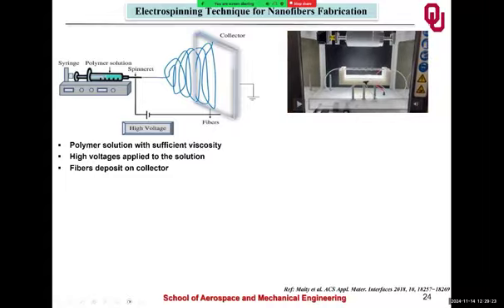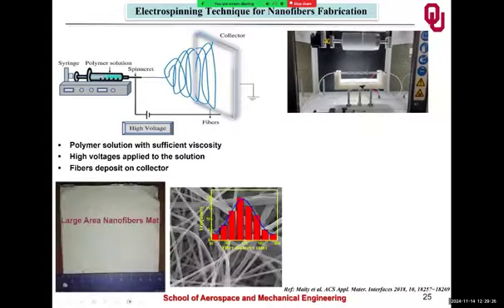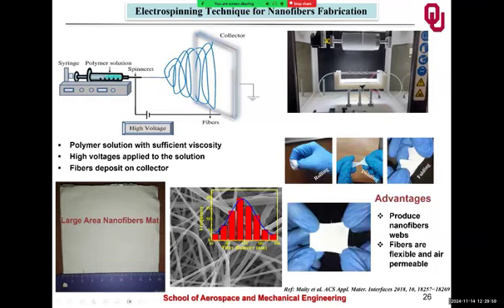One advantage of this technique is that we can get a large area nanofiber mat. And if we look under the microscope, the fibers are actually in the nanometer range. The diameters are in the nanometer range. Here you see mostly fibers around 100 nanometers, and we can tune the area. Where other techniques are constrained in large area fabrication, the electrospinning technique comes up with a new idea that we can get large area. And these fibers are very flexible, air permeable, and we can twist, roll and fold.